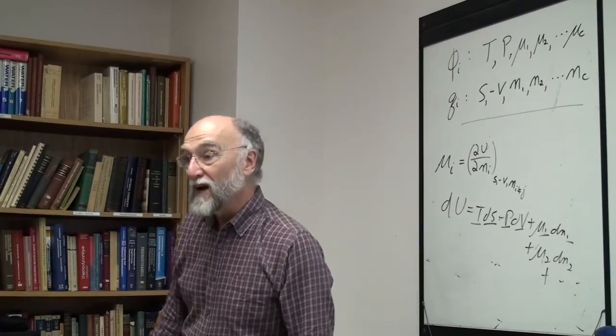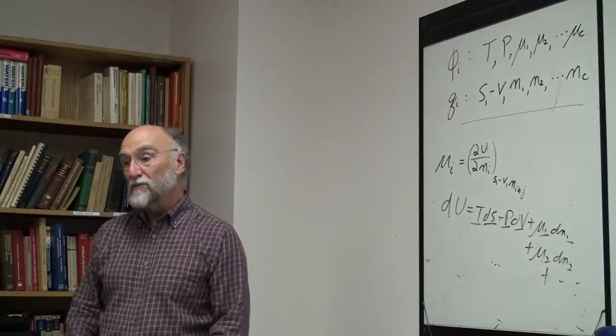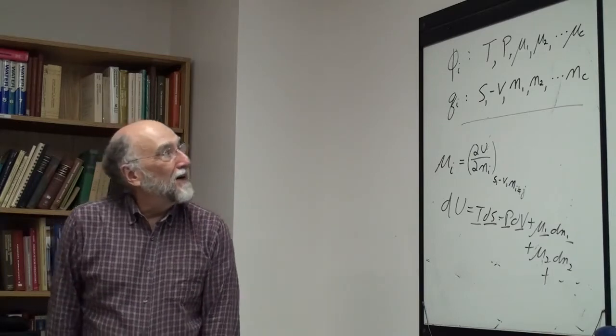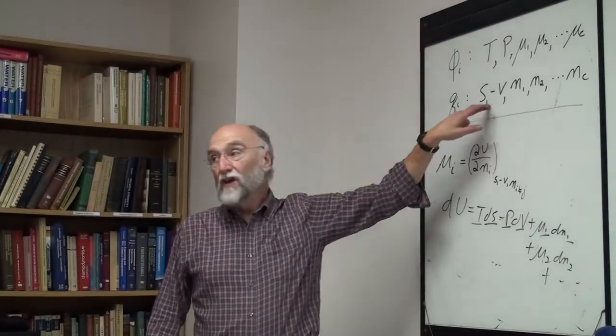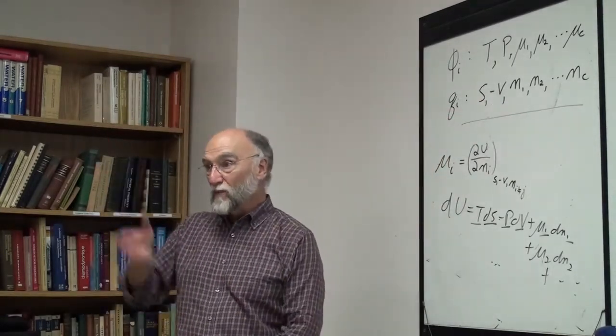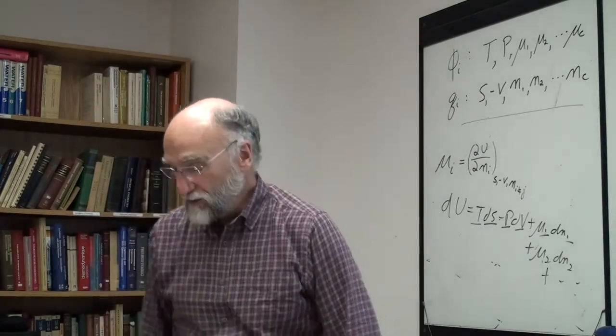So if you have a diagram where the only things that are constant are temperature, pressure, and chemical potential, then everything lies in the diagram. If you keep a certain number of moles or a volume or something constant, then you have a diagram where the tie lines do not necessarily lie in the plane of the diagram. We'll give you an example in a minute or two. So if the only variables held constant are potential variables, then the compositions of all phases will lie in the plane of the phase diagram, and the lever rule may be applied.